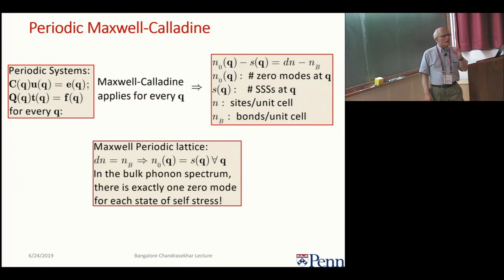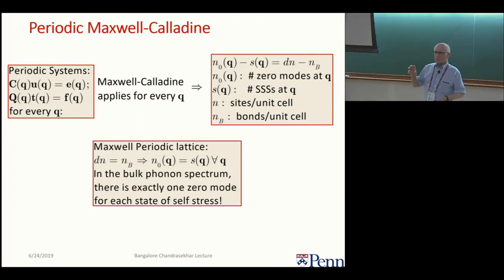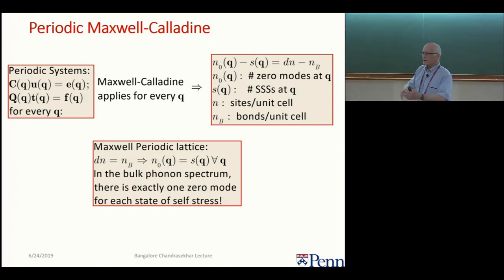Now, I'm interested, I don't have to restrict our attention to this, but it turns out that it's a sufficiently rich field that I want to look at Maxwell lattices, which are periodic. And that means that Q, the wave number, is a good quantum number, if you wish. And this big matrix, which is dn by nb, I'm taking nb equal to dn because we have a Maxwell lattice. So we have this dn by nb dimensional matrix, which breaks up into subblocks of dimension of the unit cell.